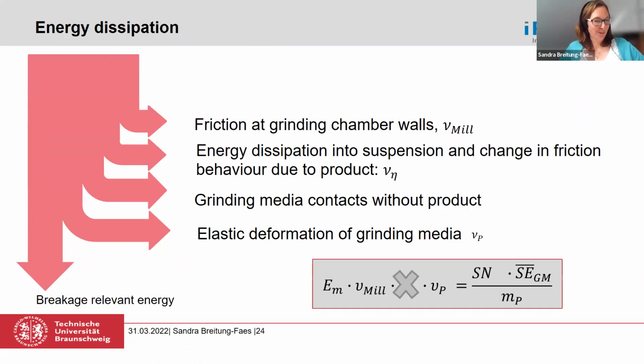Okay, and then I would shortly come back to this diagram because there is one thing I am still missing when we want to calculate the energy. And this is this mill energy transfer factor. Here I had certain ideas how to do it. My first idea was to run the mill only with the liquid phase and to see how the power consumption changes when running the mill with the suspension, because I thought the suspension will play a role. At least I have to say this did not work. We tried it, but we saw very clearly that there was no connection which could really be found.